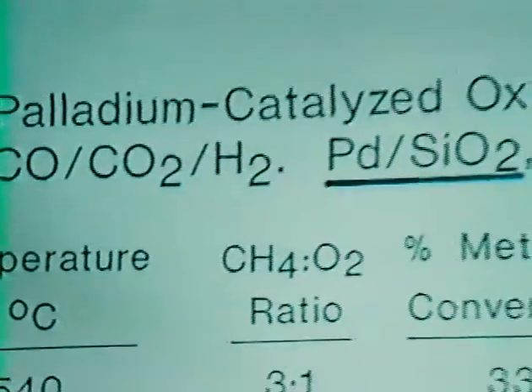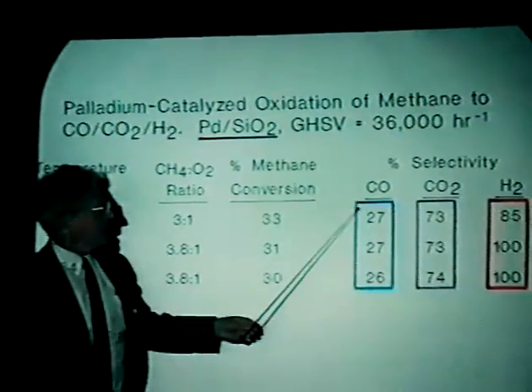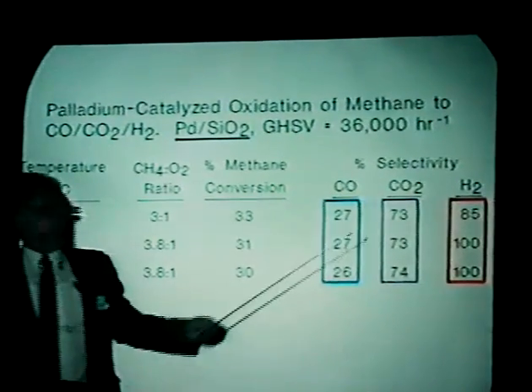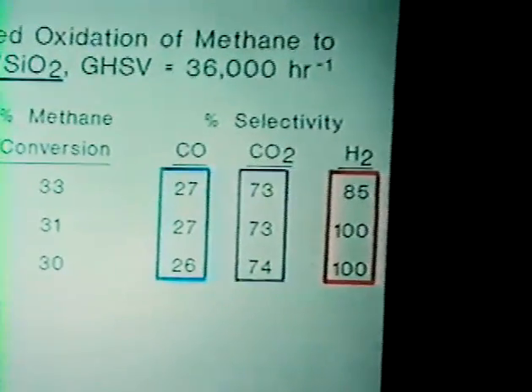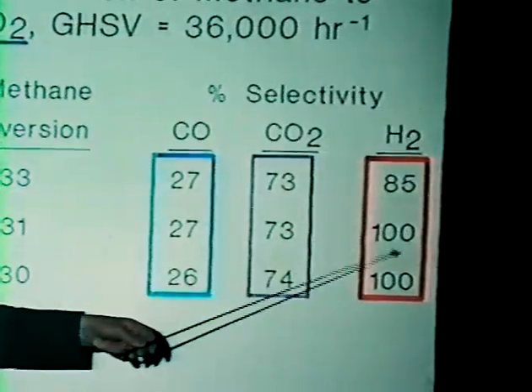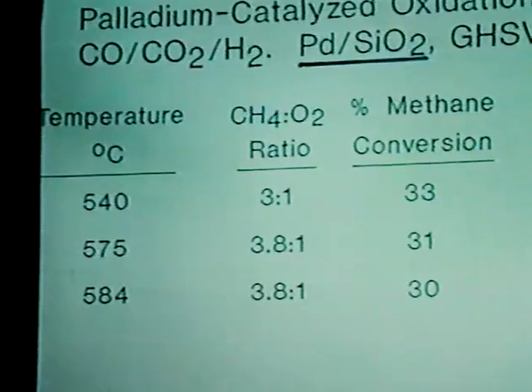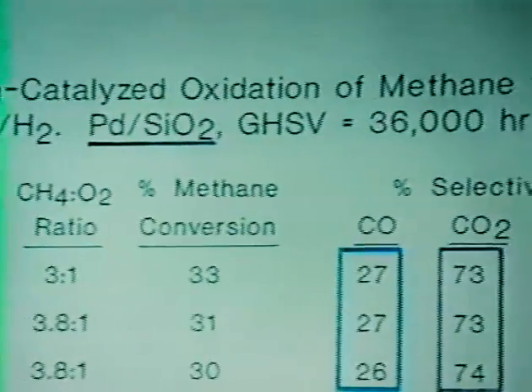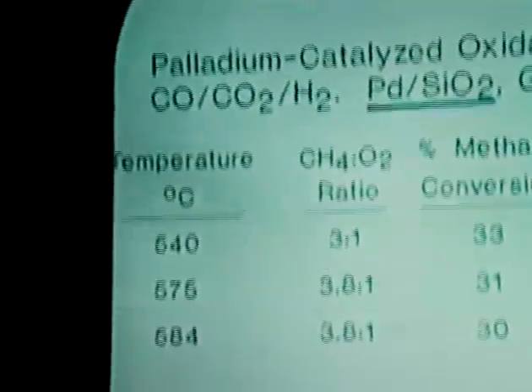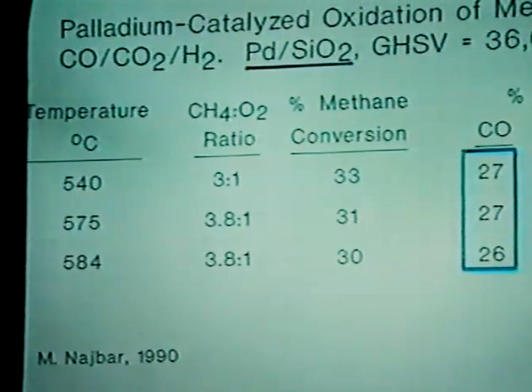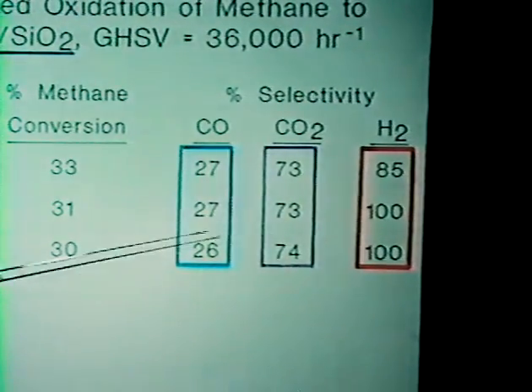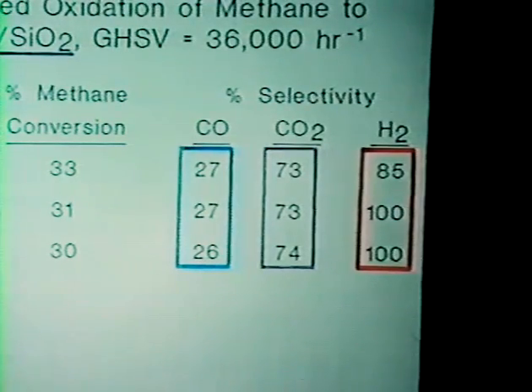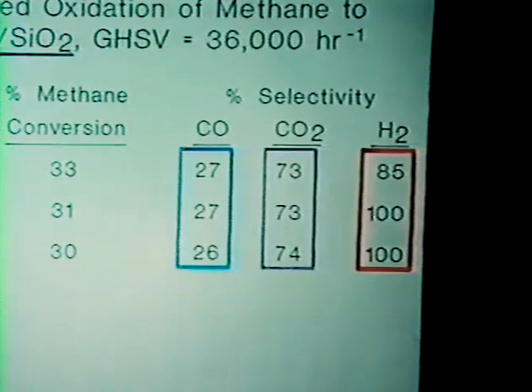Now, if you do this in a flow reactor on supported palladium, most of the time you will find a product which is carbon dioxide and water. But if you have the conditions right, your products are carbon monoxide, carbon dioxide, and hydrogen. And if the selectivity to hydrogen is 85%, this is a selectivity between hydrogen and water, that means 15% water is formed. But if the selectivity is 100% to hydrogen, that means, like on the single crystals, no water is formed. So we are oxidizing methane to carbon monoxide, carbon dioxide, and hydrogen. In other words, we're making a synthesis gas by direct oxidation, not by steam reforming. And the selectivity to hydrogen is truly remarkable, but the conditions for this reaction to occur this way must be found very carefully. And palladium is one of very, very few metals that it will actually produce hydrogen.